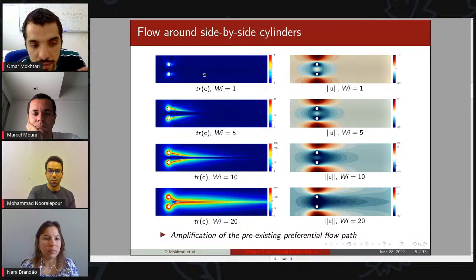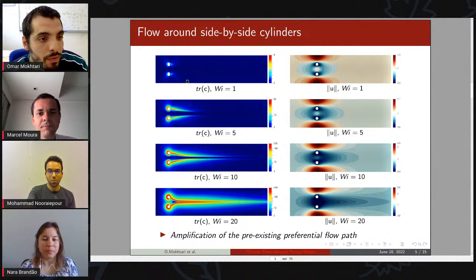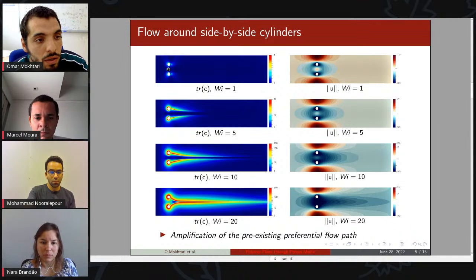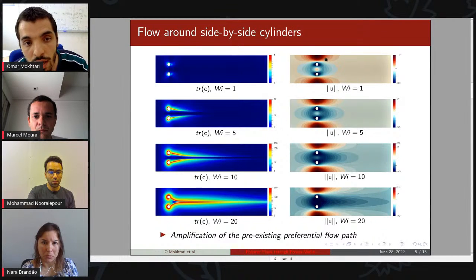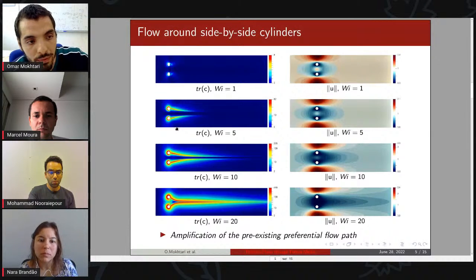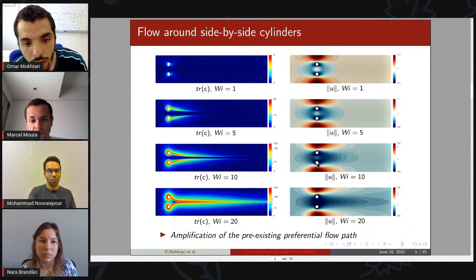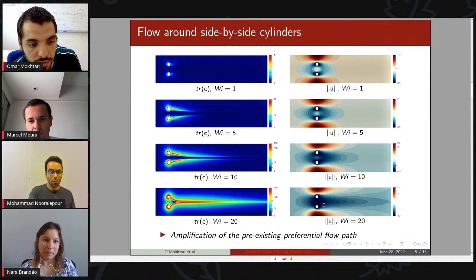Now, if we consider two cylinders, this is a very interesting test case where at the beginning, due to the gap between the two cylinders, we have a pre-existing flow around the two cylinders, and the flow between the two cylinders is smaller. Because of this pre-existing preferential flow, the strands are curved. So by increasing the Weissenberg number, the two strands go closer and closer, until they touch. So at the end, we can observe that we have no more flow between the two cylinders. This is a very important mechanism of amplification of pre-existing preferential flow paths.